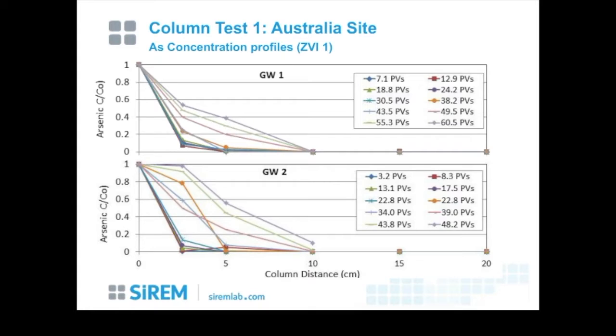And as you see, the iron is getting used up or passivated, and so we see a progression of arsenic profiles. Arsenic 5 gets reduced to arsenic 3 and then complexes with iron and creates solid phases. So it creates passivation because it blocks the iron surfaces and doesn't allow it to be reactive any longer. And so you can see in groundwater 1, we did 60 pore volumes. And you can see that at this port here that I'm pointing to, at 60 pore volumes, we had breakthrough of the arsenic, whereas at 7 pore volumes, it was much less.